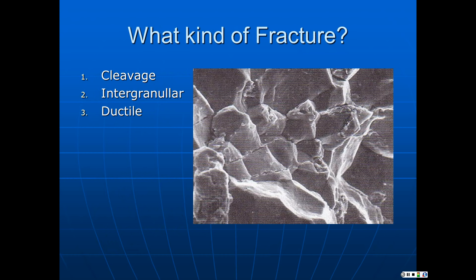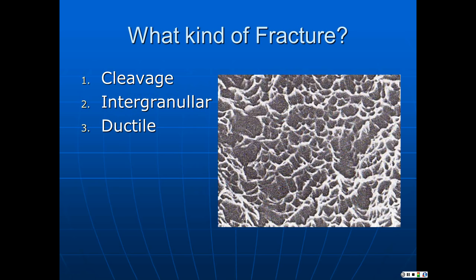What kind of fracture are we looking at here? If you answered intergranular, you're correct. You see the chunkiness, and you also see some cracks in the surface suggesting that grain boundaries growing into the surface are also failing — all of those suggest a breakdown of the grain boundaries. And what kind of fracture is the next one? If you said ductile, then you're right on the nose. You see voids — holes in the surface. This is a heavily voided surface with lots of small defects. Ductile fracture.